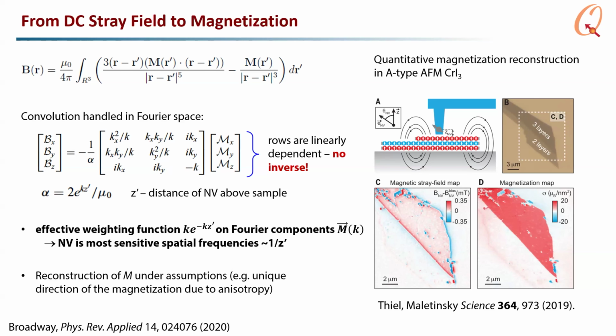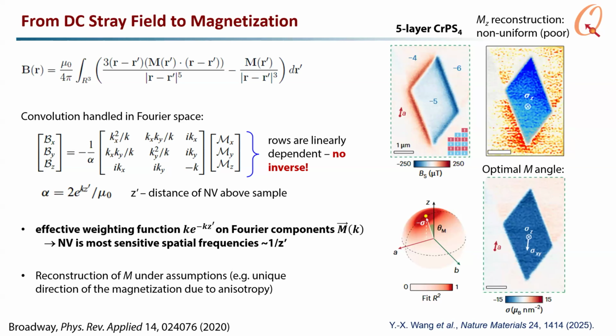Okay, so we did this actually recently. We've worked with another 2D antiferromagnet, chromium thiophosphate, CrPS4, and this is our data on a 5-layer section. And here we can reconstruct the magnetization, but the magnetization is not purely along the z-axis, or the AB axis. It's actually tilted, and we find this by trying to get the most uniform magnetization over the area of the flake. So if you assume a purely z out-of-plane magnetization, the reconstruction will show spurious gradients, whereas the magnetization at the optimal angle gives you a very uniform magnetization over the flake.